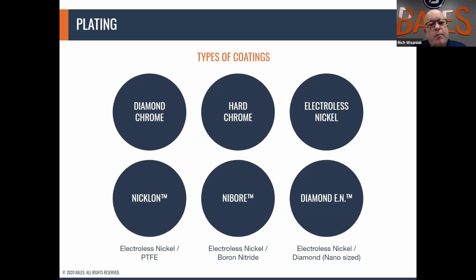Nicklon, which is nickel PTFE, is one of the early hybrid coatings in the industry, which is great for lubricity and also excellent on your LSR tools and your rubber molds. Nibore, nickel boron nitride, is the slickest we have, with a coefficient of friction of 0.05 or less. If you've got a sticking problem, and it's pretty much most resin materials, Nibore is the way to go.